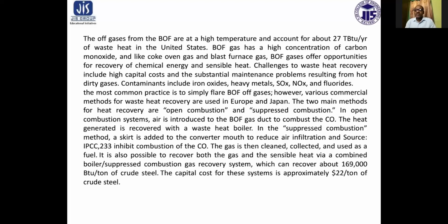The off gas from the basic oxygen furnace is at high temperature and accounts for 27 trillion BTU per year of waste heat in the US. This gas has a high concentration of carbon monoxide, like coke oven gas and blast furnace gas. These gases offer opportunities for recovery of chemical energy and sensible heat. Challenges to waste heat recovery in these gases include high capital cost and substantial maintenance problems resulting from hot dirty gases. The most common practice is flaring of the gases, however, this varies.